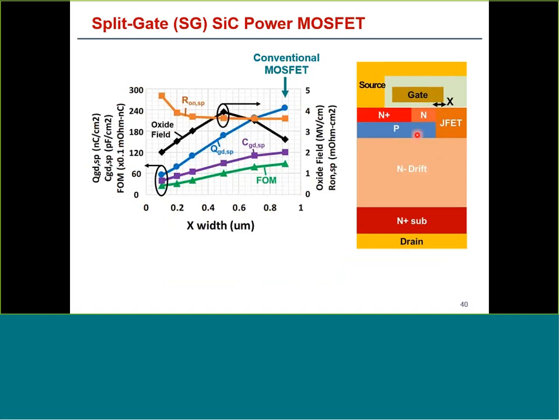I should point out that the JFET width in our design has a value of 0.9 microns, it's right here. As a consequence, when X becomes equal to 0.9 microns, we end up with a conventional structure. So if we reduce X, then we start getting lower and lower values for CGD as expected, and QGD, of course, also goes down. And this results in significant improvements in switching behavior.